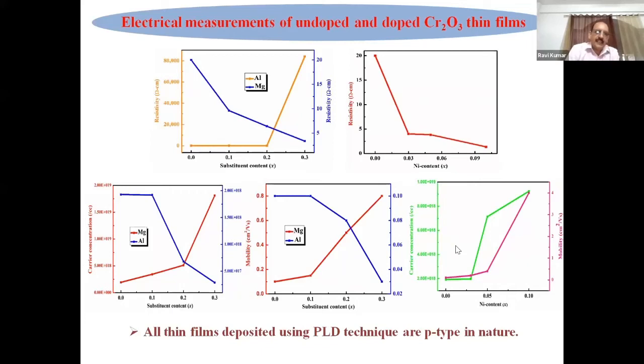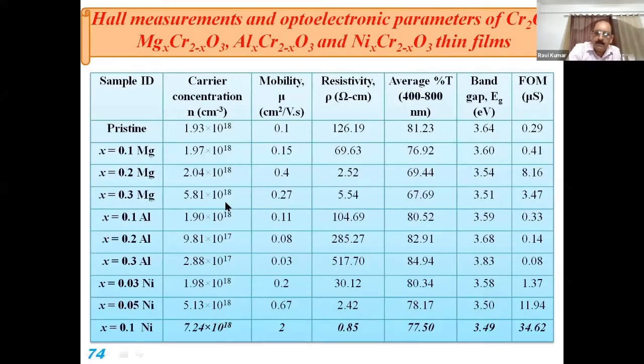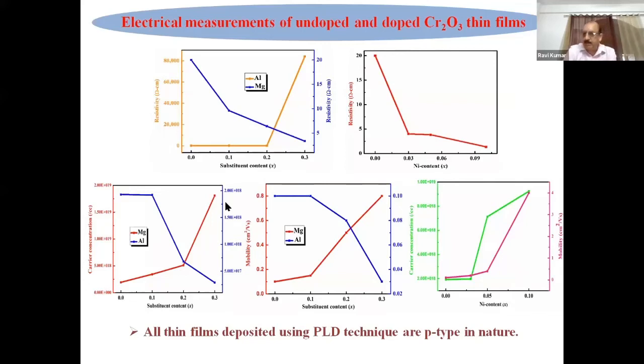Another is the carrier concentration. Now you look at the carrier concentration: it is increasing up to 10 to the power 19 carriers per centimeter cube, whereas in the case of aluminium, the carrier concentration is decreasing. In the same way, the Hall mobility is increasing for magnesium, whereas it is decreasing for aluminium because it's already an insulator. The carrier concentration in the case of nickel is also very high, and the Hall mobility is also increasing to a higher value, even higher than magnesium.